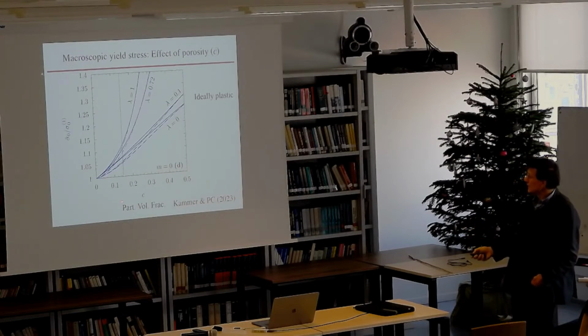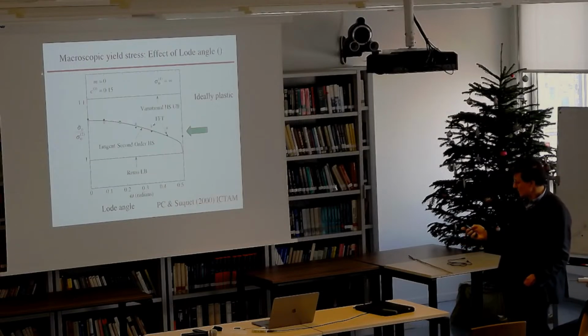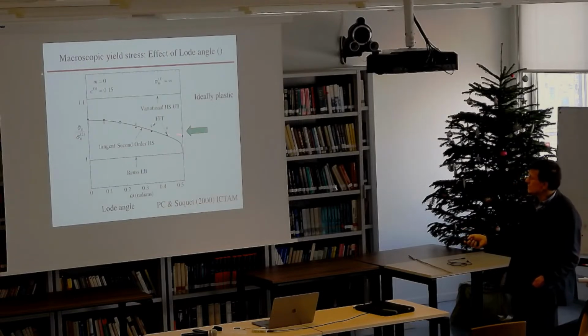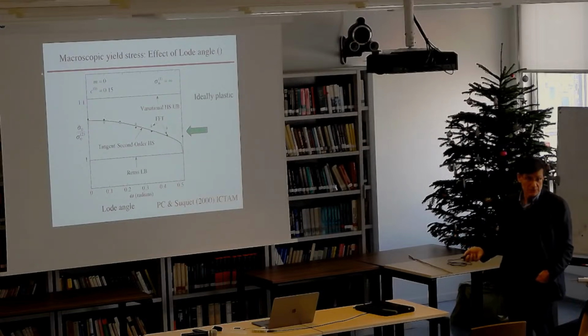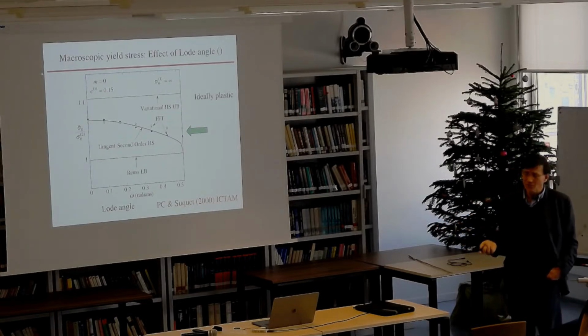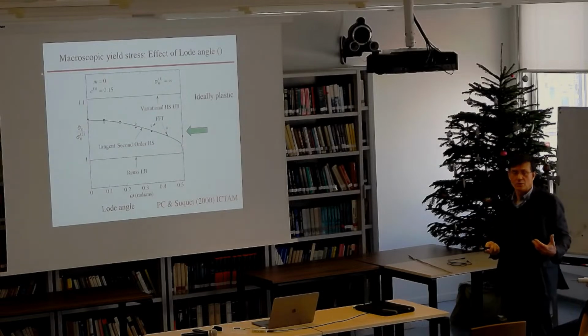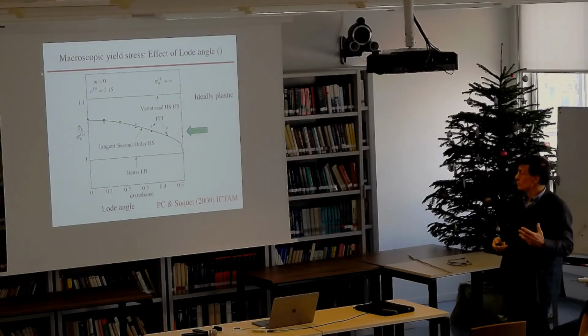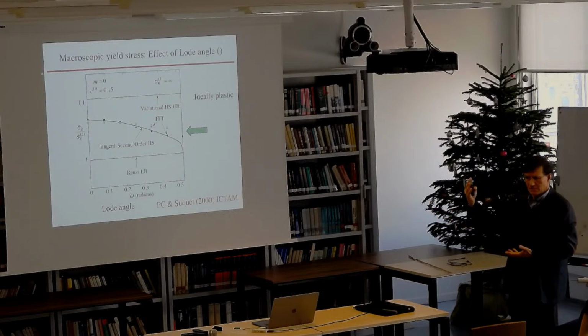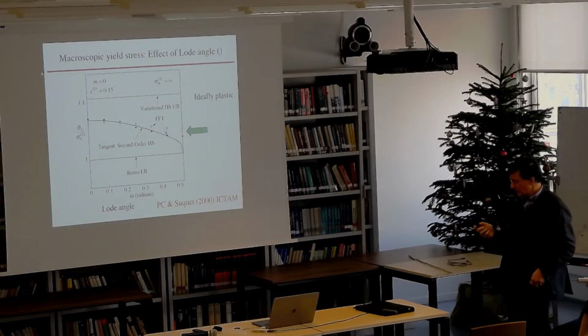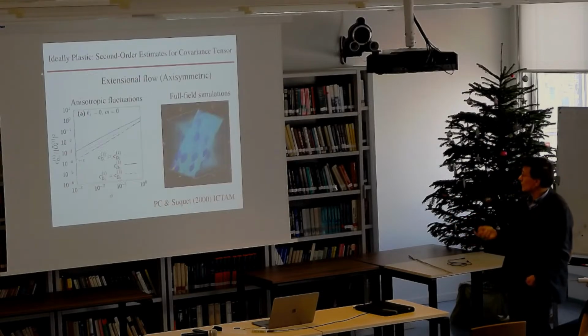But if you look at that volume fraction here, you see that you don't go from here to 0, you go from here to there. We haven't done the comparisons yet, but it's consistent with the FFT results. With the second order method, particularly this fully optimized second order method, in cases without strong fluctuations, the tangent second order method works pretty well. But for situations like shear bands, you need this more sophisticated, fully optimized second order method that accounts for the fluctuations.